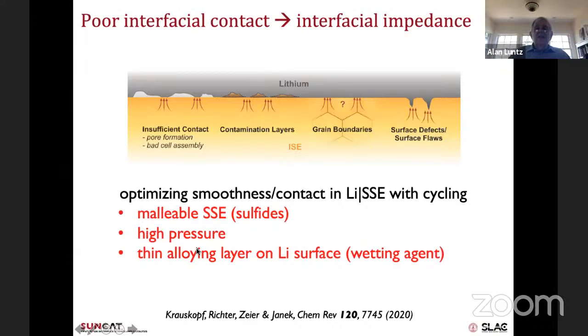If you apply high pressure, you can squeeze the things together and make good contact. But again, that's maybe an issue in practical batteries, but not in the lab. And then it turns out there's a way to put a thin layer of materials that alloy with lithium, like germanium or gold or something like that, on the surface of the lithium, it acts as a wetting agent. And as you grow the lithium, it tends to float on the surface and act as something of a wetting agent. Exactly how that works is not known, or at least by me. I think it has a lot to do with lowering the nucleation overpotential for forming lithium on these surfaces. And so it grows at lots of places at once instead of just growing on one crystal at the defect.